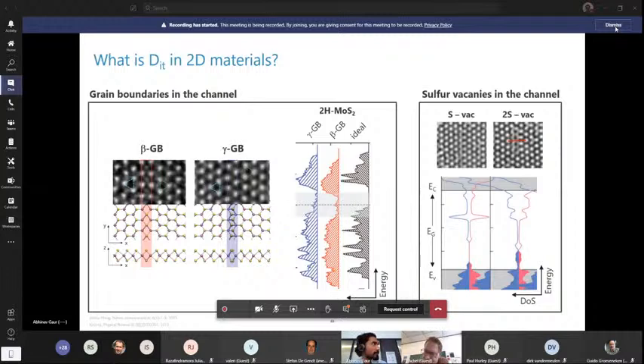Well, I think so. From what I understand about physical defects on 2D materials based on TEM and all these things, we still have beta type and gamma type grain boundaries in our material. So if Professor Stesmans is looking at CVD material, then it is highly likely that there are a lot of beta and gamma type grain boundaries. And they are not specifically sulfur vacancies or something like that, right? They are a broad distribution. They can be anything. They could be antisites or vacancies or interstitials, things like that. So that might end up showing a broad distribution.